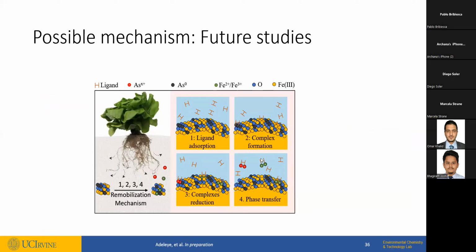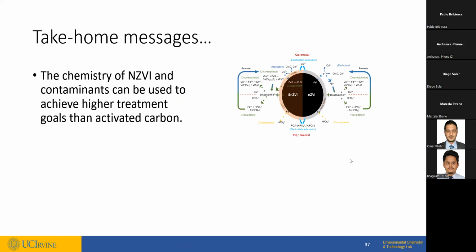And this is sort of a hypothesis of how the increase in leachable arsenic may have resulted from the exudate released by the plant. So the ligands that may be present in the root exudate can complex with the surface of the structure formed by the nanoparticle and our metallic contaminants. The ligands are electron donors, so they can complex some of those iron oxides. And if they complex and reduce them from Fe3 to Fe2 state, for instance, there could be phase transfer, which means some of the arsenic that was previously immobilized in the structure of the nanoparticle can be released back into the aqueous phase. And with that, I would like to wrap up.